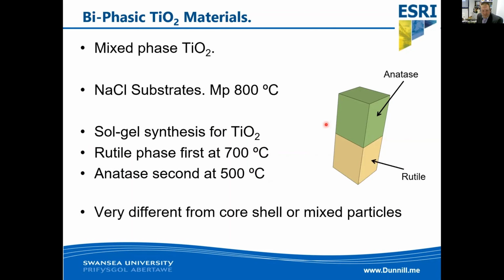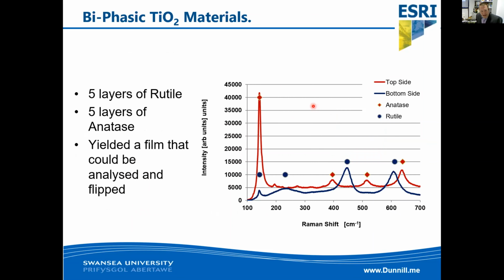And note that these are actually very different from core-shell particles, where one phase is completely encased by the other. Both of these phases are freely accessible to both the light and the water. We did a synthesis like this where we got 5 layers of rutile followed by 5 layers of anatase, and it yielded a nice film that we could flip over. So this is Raman spectroscopy, where we can see on the top side we have a very good match for anatase, and on the bottom side we have a very good match for the rutile. So that shows you how the synthesis works.